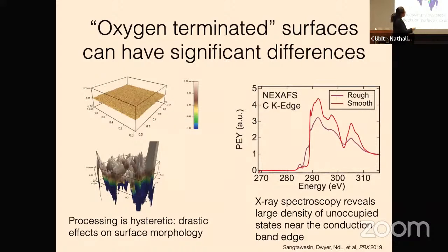And we could see a direct consequence in the X-ray absorption spectroscopy in the electronic structure. So this is NEXAFS, which is basically a probe of the unoccupied density of states. This sharp peak here is the exciton edge of diamond. So everything to the right should be there. It's the conduction band structure. But then everything to the left is just defect states. And you can see that for this rough surface, you have this huge density of defect states that are near the surface, which are suppressed for the smooth surface.